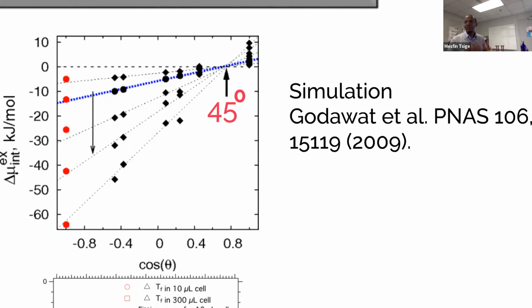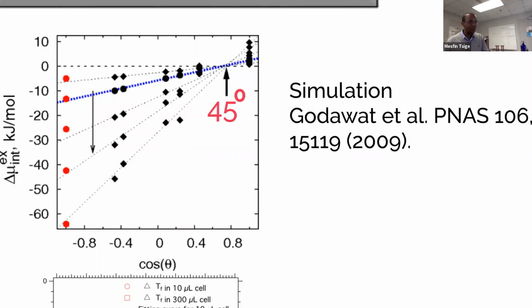So they came to the conclusion that the definition of the hydrophobic to hydrophilic transition should really be on a molecular level, and 45 degrees should be the angle that we look at instead of 90 degrees. This is pretty much from the simulation side.